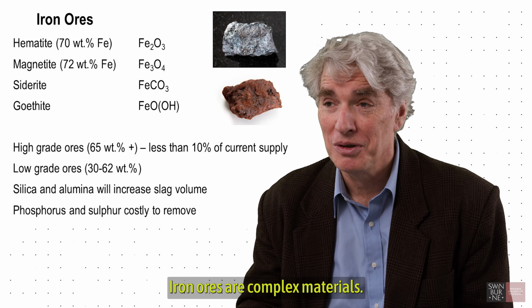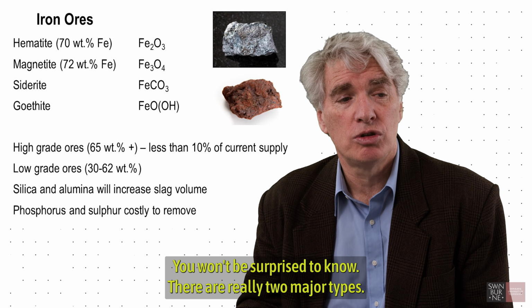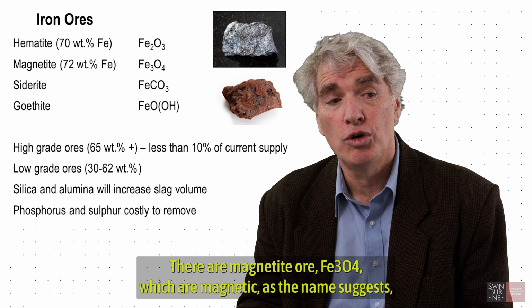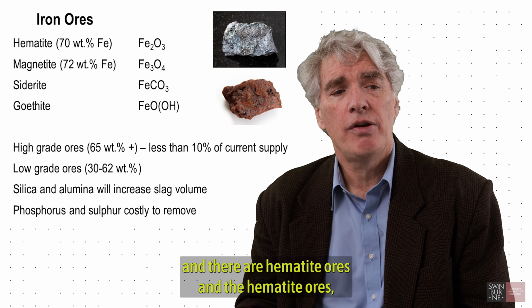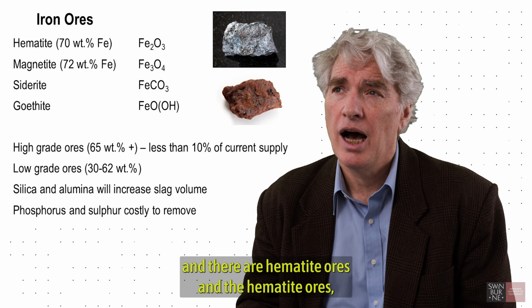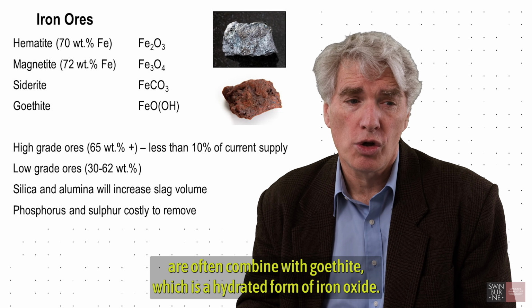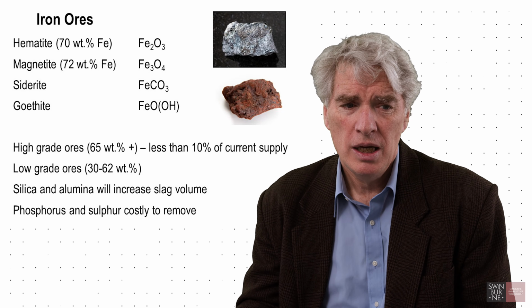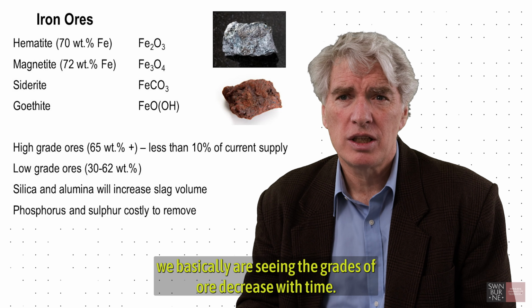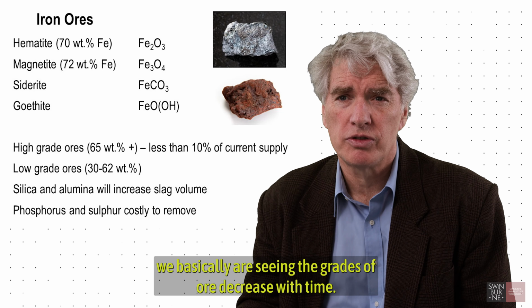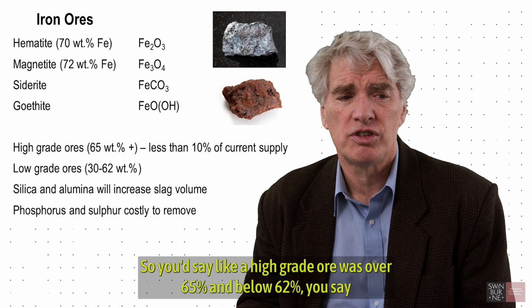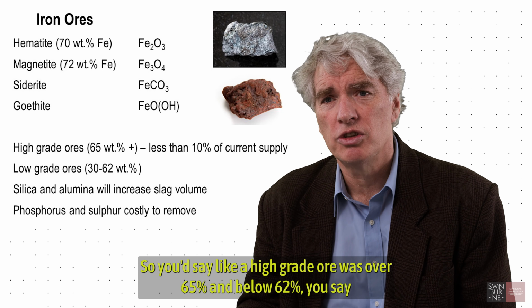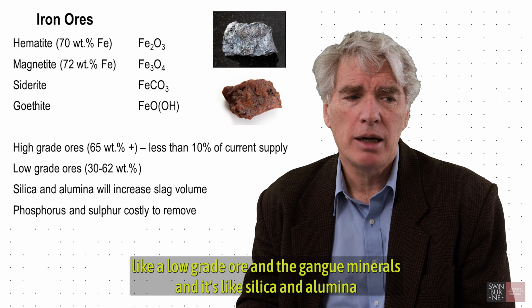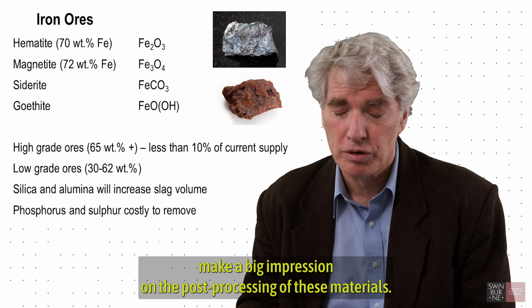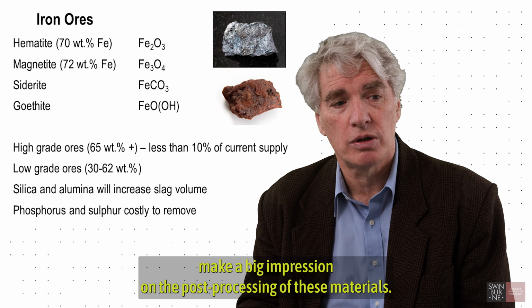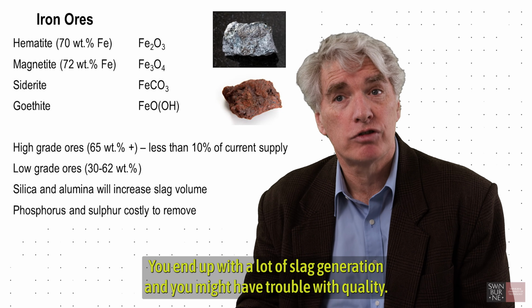Iron ores are complex materials, you won't be surprised to know. There are really two major types. There are magnetite ores, Fe3O4, which are magnetic, as the name suggests, and there are hematite ores, and these hematite ores are often combined with goethite, which is a hydrated form of iron oxide. And at the moment, we basically are seeing the grades of ore decrease with time. So you'd say a high-grade ore was over 65%, and below 62% you'd say it's a low-grade ore. And the gangue minerals in this, like silica and alumina, make a big impression on the post-processing of these materials. You end up with a lot of slag generation, and you may have trouble with quality.